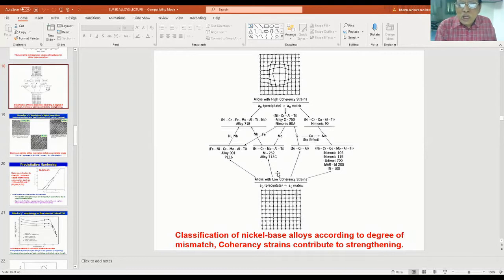Like that, so many alloys are derived from one alloy to the other by adding some elements. For example, here you can see that initially nickel, chromium, aluminum is there, which is developed. Then titanium has been added, and the alloy known as Nimonic 80A has been developed. So alloy X-750 has been developed. That is the way the tailoring of the composition and manipulating of the microstructure has come in.